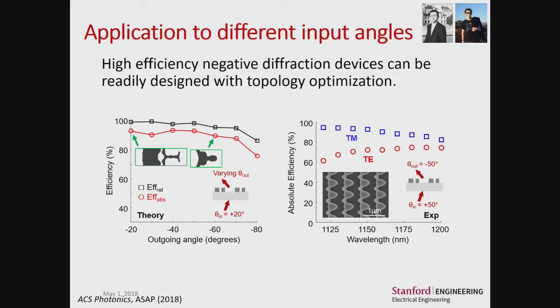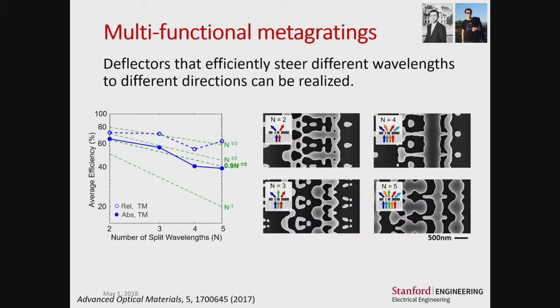But as we consider correcting for practical aberrations, such as coma in aperiodic devices, optimizing in ways that can incorporate non-normal angles is important. In this case, here's an experimental demonstration of a device that takes in 50 degrees and outputs minus 50 degrees. Here we can see for both TE and TM that we have relatively high absolute efficiencies. And in this case, we've applied topology optimization to make multifunctional devices, which is quite difficult to do with conventional means.